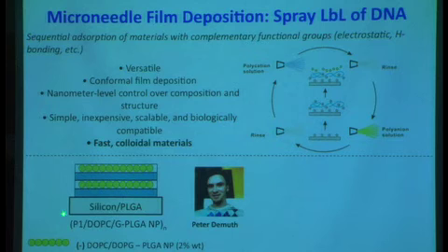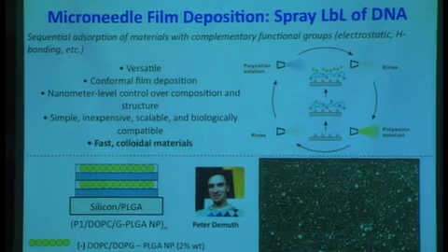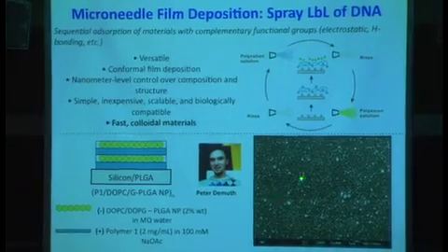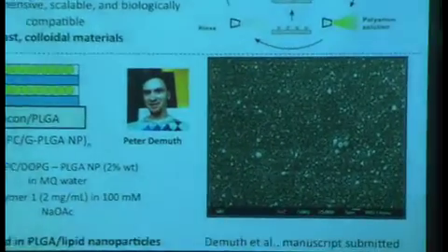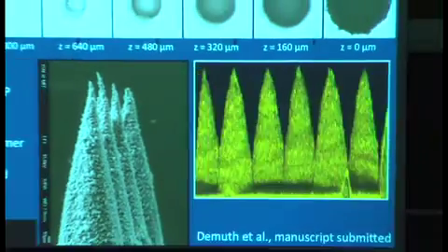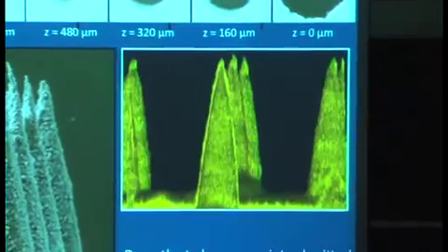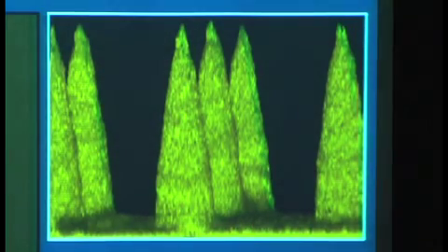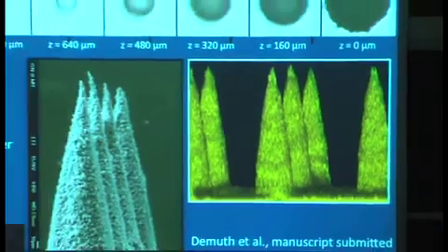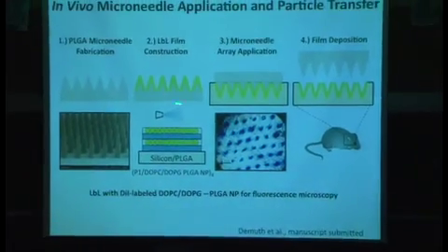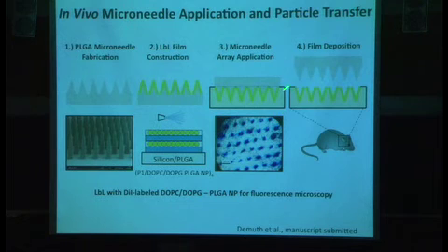Here we're actually using a very simple system, our degradable polyester, which is a positively charged polymer, with a negatively charged PLGA particle. It's negatively charged using a lipid layer. And this is an example of what these films look like when they're built up. You can see the particles quite clearly in these layer-by-layer films. So we've been able to actually coat these very effectively. And as you can see, you get coverage across the entire microneedle surface, as shown here. When you transfer them to the mouse skin, you actually deliver the entire film, and you can remove the stamp.